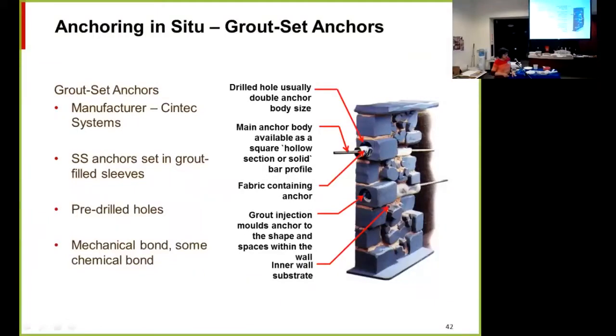Grout set anchors are for where you have more of a rubble wall and you can't really put in an epoxy anchor because you would just end up filling the wall with epoxy. And so this has a sock around the stainless steel pin and you fill it full of grout and it just fills up that empty space and anchors the facade.